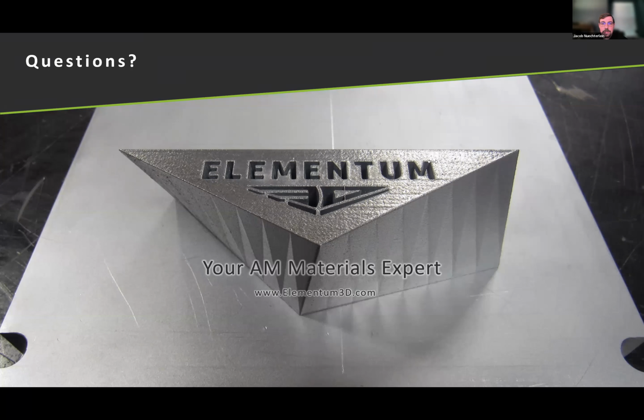Scan strategies. So scan strategies, I think, is a really important piece of this. We've done a lot of different things looking at scan strategies on copper, including double scanning. The problem with double scanning is then you start to lose the advantage of the powder being rough, so you don't then get the reflections and the extra reflections. We found that once you melt the material, that material then is very reflective, and therefore it's a lot more difficult to put more energy in.